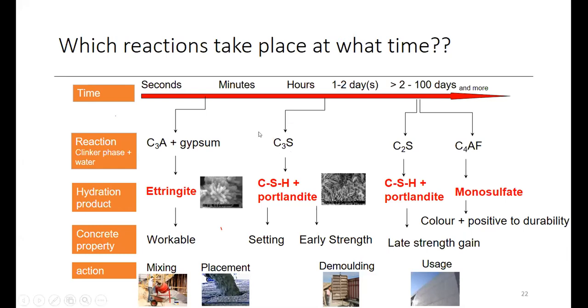So with the reaction of C3S with water, meaning H, they form CSH gel. Since it's a gel, it's actually not a very soft gel, but a gel-forming material. We call it CSH plus OH minus, which means calcium hydroxide, called portlandite. The same reaction happens with the C2S as well.